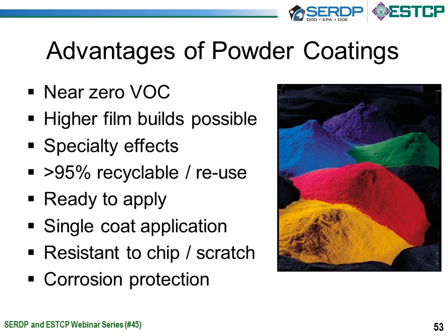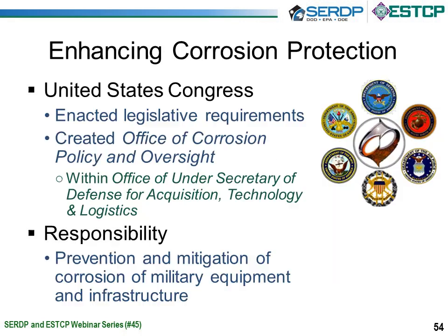You know, the same: resistant to chip, resistant to scratch, and corrosion protection. So whether we're talking about a powder or a primer, there are ways and means that powders can be applied. For example, the Faraday cage effect with application allows the electrostatic wrap so that those corners of a part that are difficult to coat or difficult to achieve the correct film build on is much more effective to do with a powder coating. You're not getting too high of a film where you're getting dragged. You're not getting too thin because you're not getting enough electrostatic wrap to it. So powder coatings are known for improvement with that.